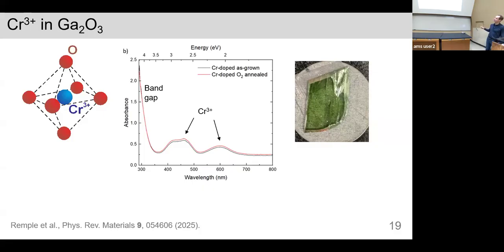These are the absorption bands due to the electronic transition. This is the bandgap of gallium oxide, which is around 4.5 electron volts. So that's the fundamental absorption. And these absorptions are due to the impurity. And that gives it the greenish color.